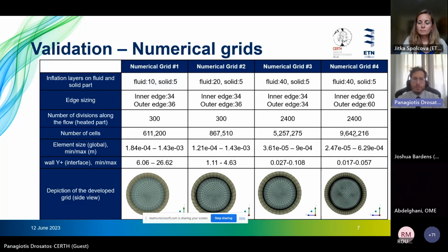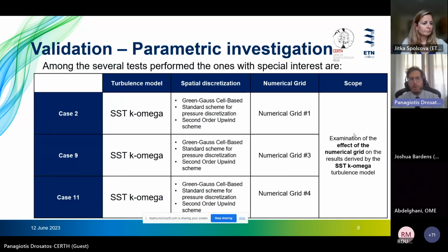In the framework of this procedure, we develop and utilize 4 different numerical grids, starting from coarser and ending up to very fine numerical grids in order to span a wide variety of grid densities and y+ absolute values, starting from very high and ending up to very low absolute values, even lower than unity. Among the several tests we performed, we selected to present these 3 indicative ones, case 2, case 9, and case 11. All these 3 cases present